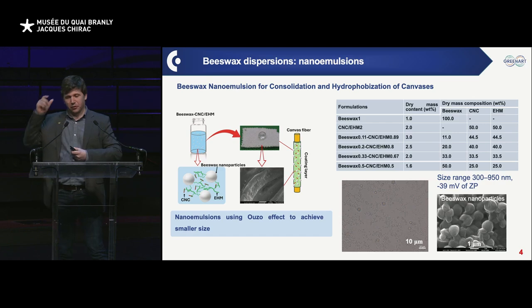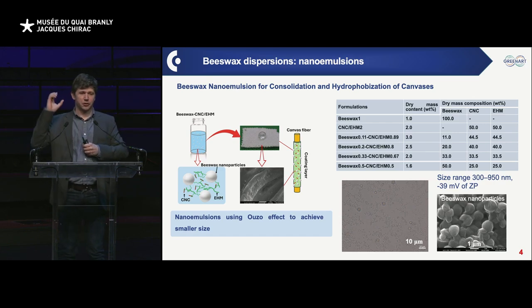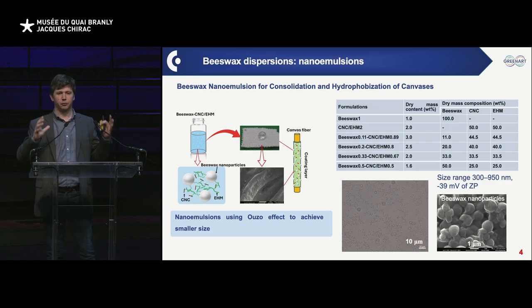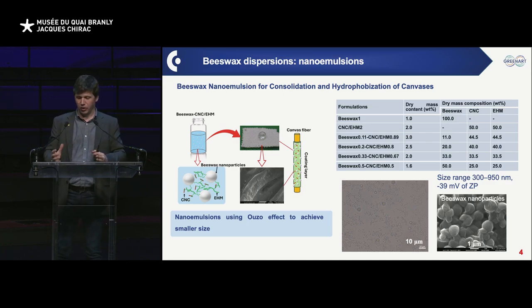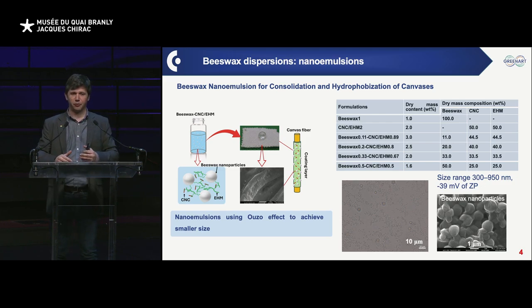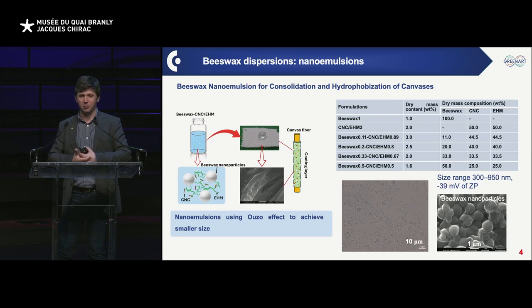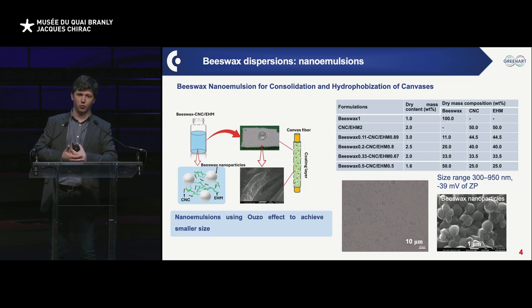Then, based on that, we were very happy, but still the particles I was showing you now were like 40 micrometers. So they are gigantic particles, 20, 40 micrometers. So that's, well, even though they have an attenuated effect on the surface, they may still be visible, and that's nothing we want to work with.